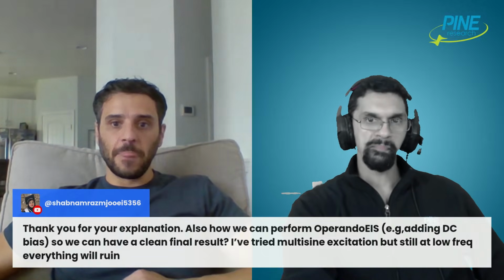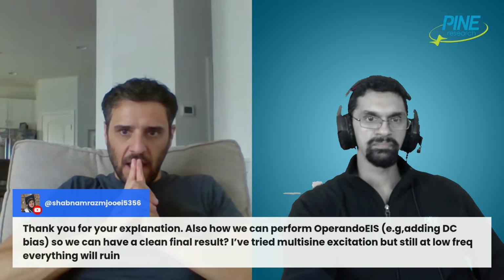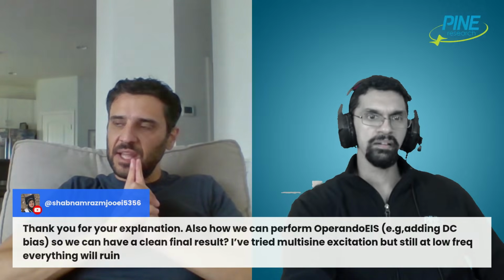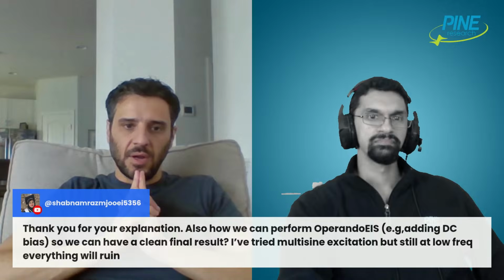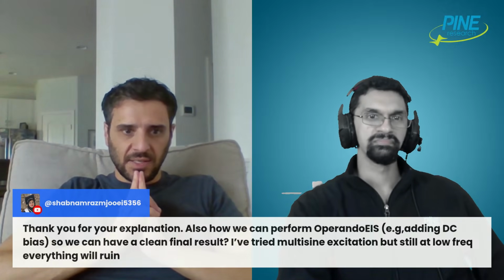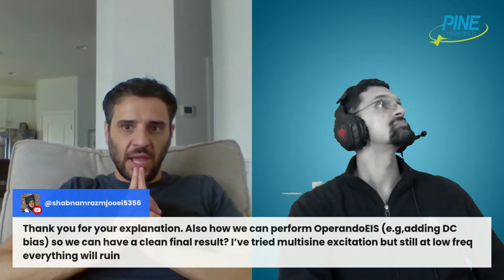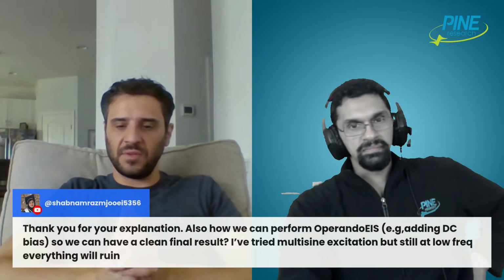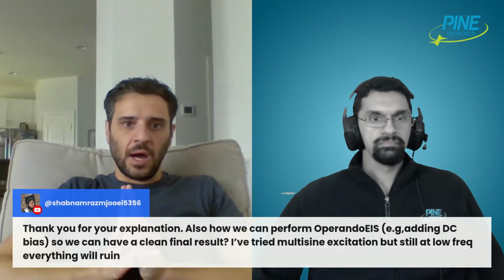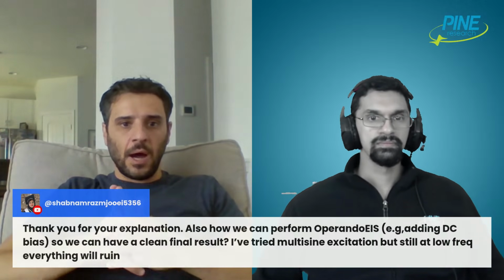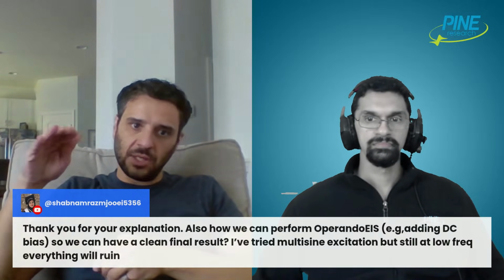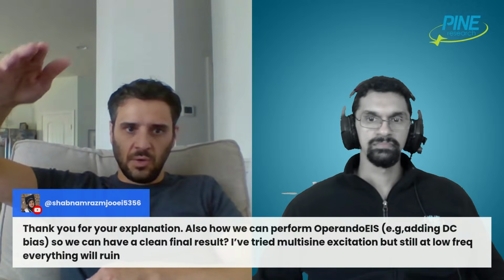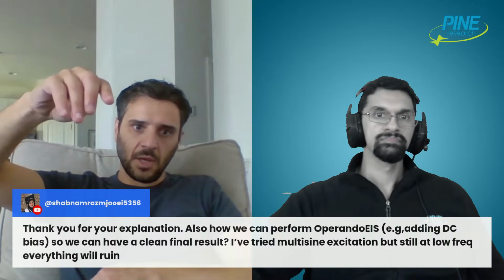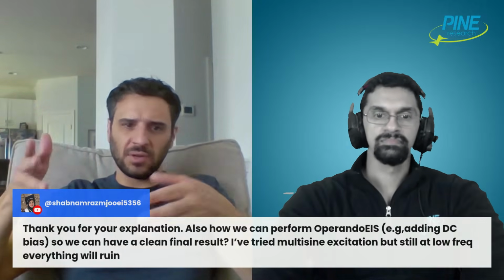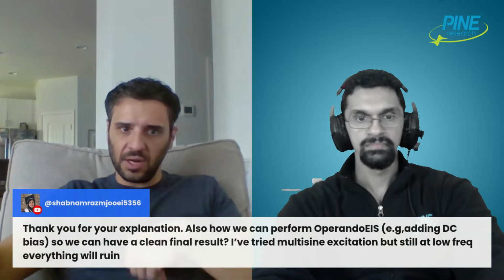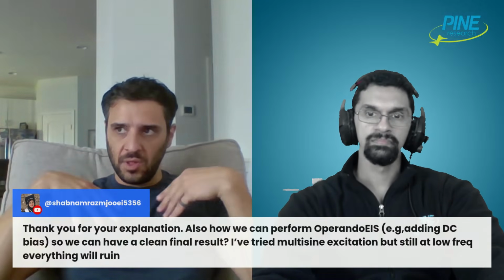Yeah, that's a good point. These things are fundamentally fighting each other. If you're adding a DC bias for a battery, it's most likely current. I'm just making assumptions here, so you can correct me if you have a different situation. Most of the time, if you're doing impedance on a battery, you're doing it galvanostatically. Okay. And typically with a battery, it's charging it to a certain point or whatever. You charge it to 50%, you let it rest for some time, and then you take impedance with no bias. It's not open circuit potential because it's galvanostatic, but you can think of it that way. It's just zero current applied. You're just taking it with no bias, right?